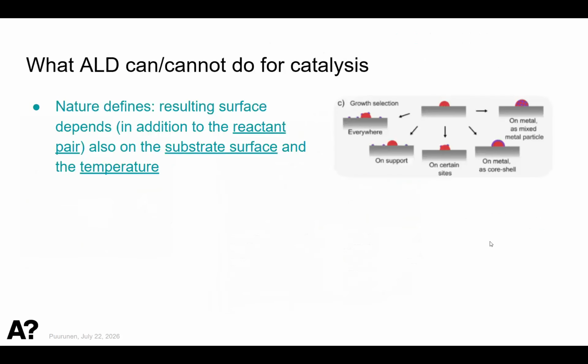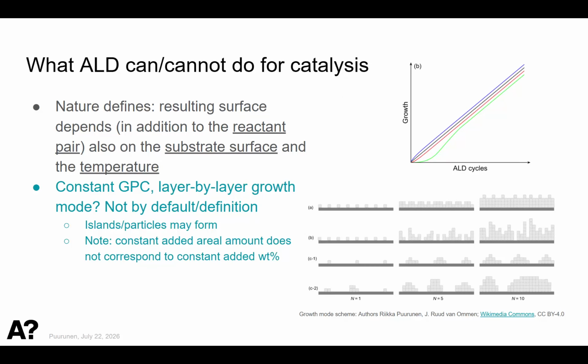Yes. All right, what ALD can or cannot do for catalysis? So there is quite some promise in this selective area growth, but it's still important also to understand that you don't necessarily get what you wish, but it's the nature that defines. So it is the reactant pair and the substrate surface and the temperature that really define where your materials grow. So you might wish for one thing and get another thing. So you need to check.